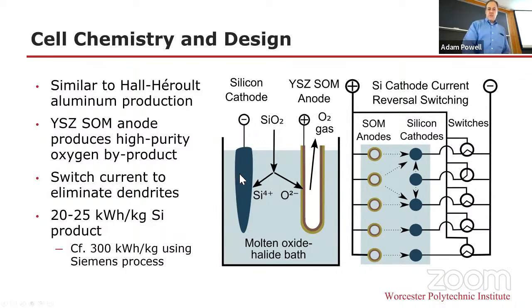At the silicon side, we reduce, it's not really Si4 plus, it's more like an SiO4 4 minus, but it's silicon in the oxidation state of 4. Gets reduced to silicon, which at this temperature is actually a decent conductor of electricity. And we suppress dendrites by periodically switching one or more of the cathodes to an anodic state. So instead of depositing silicon, we're dissolving it away from the surface. And so this is a process that I've been working on for quite a while.